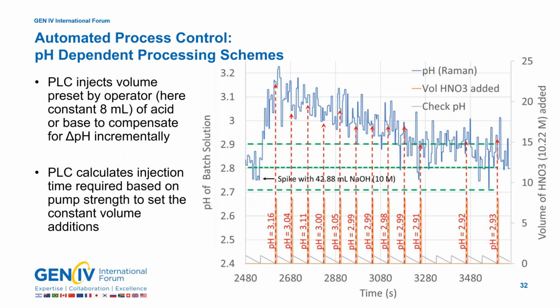The next slide shows the results of one of our experiments. The blue line here is the pH that's measured by our Raman probe, and our set point is a pH of 2.8. We have the control zone plus or minus 0.1 pH units, so at 2.9 or 2.7 pH units, that's outside the control zone. Our PLC controller will actuate a pump: if the pH is too high, it'll open a valve and deliver acid to drive the pH lower. If the pH is too low, then the PLC controller will open a different valve and pump in some base to increase the pH.